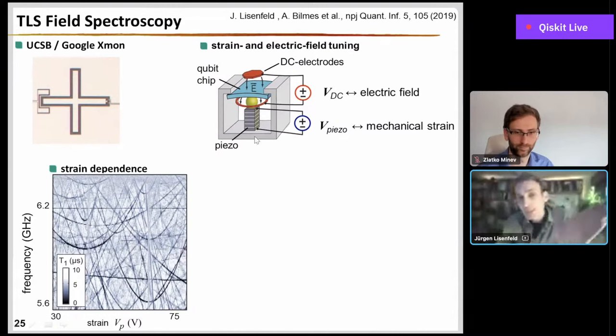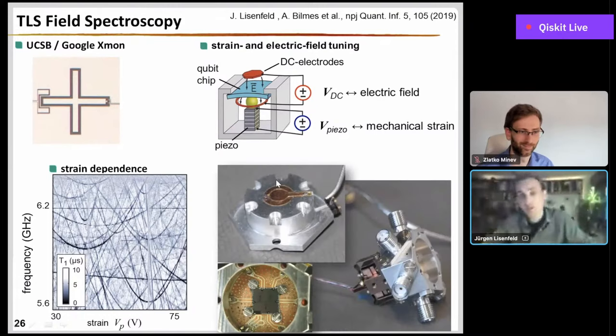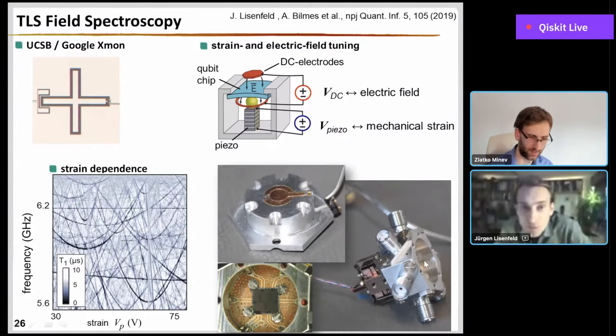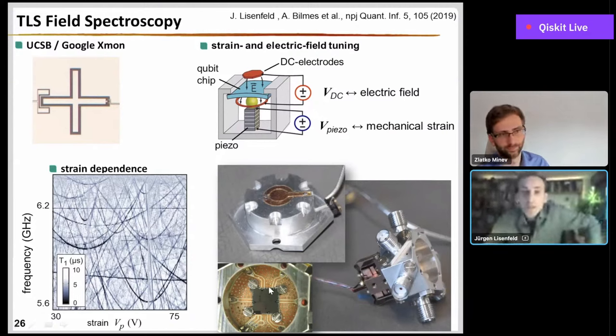And since I know that experimentalists like me always like to see pictures from the lab, here's my single picture from the lab. This is our sample housing. It's silver-coated copper. If you look inside, you see the qubit chip, which is bolted to the bottom of the sample holder using these four titanium screws. And this copper thing contains our piezo, which presses through a hole in the bottom of the sample holder against the qubit chip. By this, we control the strain, and the electric field is generated by this top electrode, which is just a piece of copper foil glued to the lid of the sample holder. The bottom electrode is just installed on the backside of this PCB chip. So it's a rather simple setup, and you can now do experiments like this.